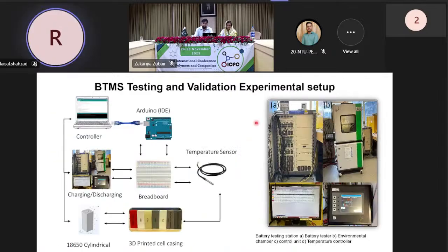After the material preparation, we start the testing, because for the battery thermal management system we need to know how it works under battery conditions. So we have environmental chambers. We have fixed the temperature at 20 Celsius, and then we have a battery tester to test the battery at different charging and discharging rates. So this is the setup for our testing, validation, and experiments. In the battery casing, we have installed some sensors in the battery pack. The sensors are highly sensitive and measure the temperature of the chamber and of the material, especially from the top, the bottom, and the middle of the battery pack.